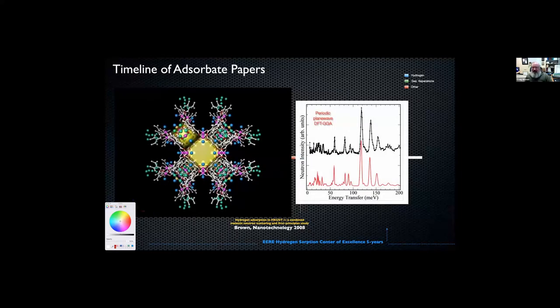In terms of the INS, clearly we can measure the neat material and look at all the vibration interactions. It's pretty much just like a selection rule less optical scattering technique like infrared or Raman. We see everything. The good thing about neutrons is that it's completely easy to get a one-to-one correspondence between a quantum mechanic calculation and that data. So you can see here that is a really good agreement on the framework.